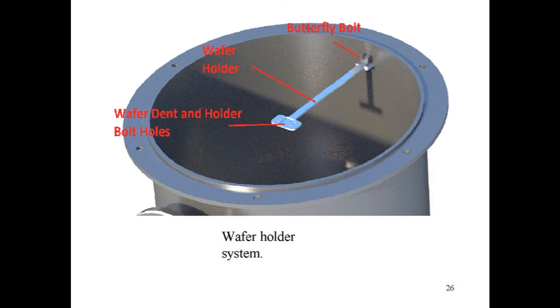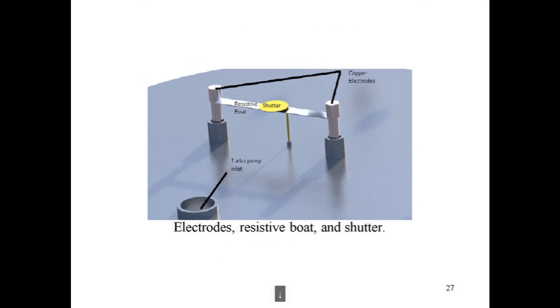The chamber has a changeable wafer holder. Put the wafer right in the holder. The holder was connected to a small interface welded on the side wall with a butterfly bolt. For resistive heating operation, ceramic coated cylindrical copper electrodes were considered together with resistive tungsten boats and a ceramic metal composite shutter. For proper deposition, the shutter must keep the source material inside the boats until the material reaches the required temperature.